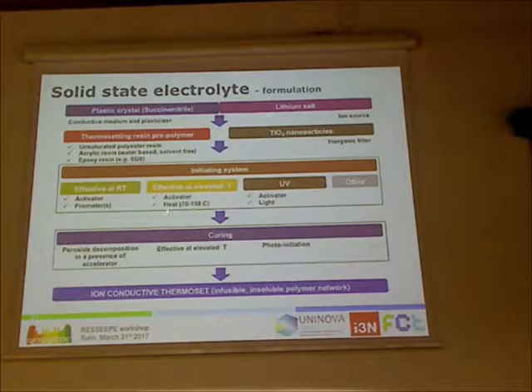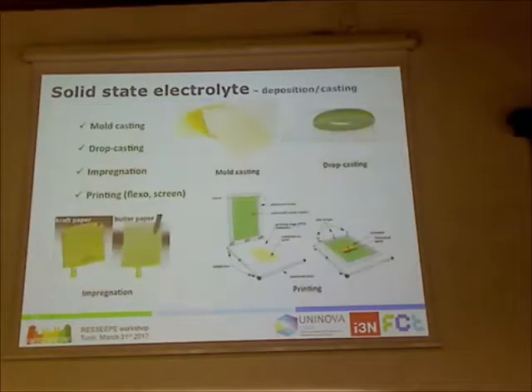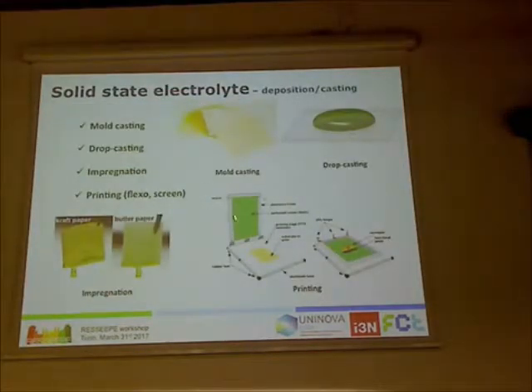and we mix what we call a plastic crystal, a molecule inside the matrix that changes conformation very fast at room temperature. This change of conformation helps the movement of the ions inside the electrolyte, even in the solid state. This can also be printed, or made on membranes like this by mold casting.